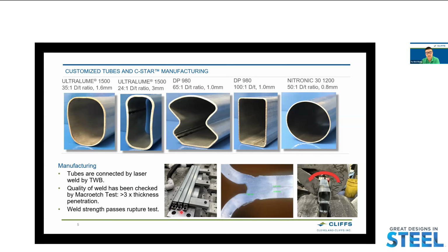They specifically designed the fixture for these applications. And the quality of the weld has been checked by macro etch. So we noticed that the penetration is more than 3 times of the thickness. This means a very robust connection, and the weld strength passes the rupture test, which is shown in this picture.